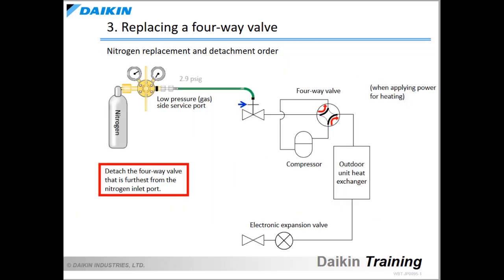After the refrigerant has been completely recovered, detach the refrigerant piping connecting the indoor and outdoor units. Send nitrogen from the low-pressure side service port to the liquid side stop valve outlet in order to replace the oxygen inside the piping with nitrogen. At this time, make sure that both the gas and liquid side stop valves and electronic expansion valves are open, and the gas side piping connection port is closed.